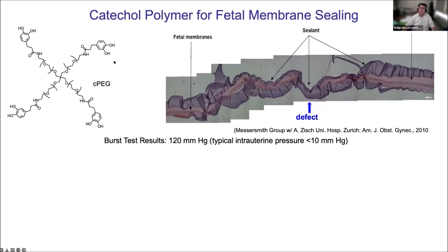This is a collage of pictures taken of a human amniotic sac that has been repaired with one of these adhesives. Okay, so the purple material here is our glue, mussel-inspired glue. Here's the defect where the puncture was made, and that's several millimeters. And the glue here attaches well to the wet tissue and bridges this defect, and was good enough to withstand 120 millimeters of mercury, which is more than sufficient for third trimester intrauterine pressure.